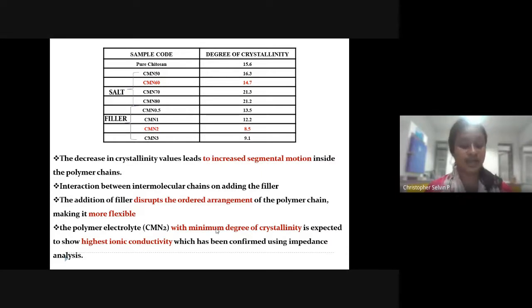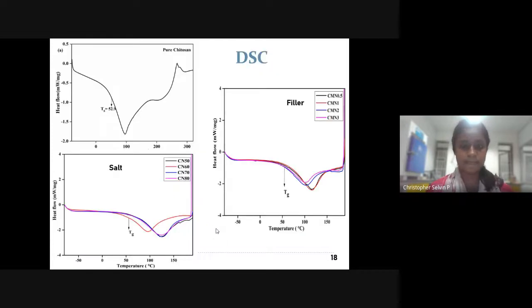on adding the filler. What happens on adding filler is that it disrupts the ordered arrangement of the polymer chain, making it more flexible, which would be confirmed with the glass transition temperature obtained using DSC thermograms. So the polymer electrolyte with a minimum degree of crystallinity is expected to have higher ionic conductivity, which has been confirmed using impedance analysis. These are the DSC thermograms of the prepared electrolytes.